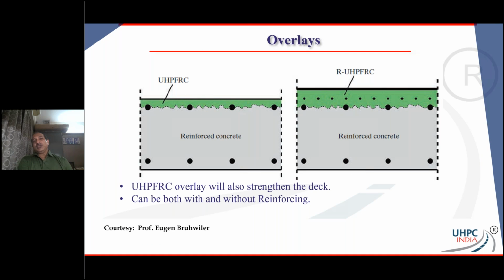overlays. UHPC, I said, it's very durable, and that is one of the reasons that it is being used worldwide as a layer over concrete bridge decks. Also on the industrial flooring. It's very good in abrasion, right? So it's used on industrial flooring as well. So if on the bridge decks, I use anywhere from about 30 mm thick to about a 50 mm thick layer, you're good against moisture penetration, against deterioration of the rebar, which is in the slab or the beams below, and you're going to have a long life.